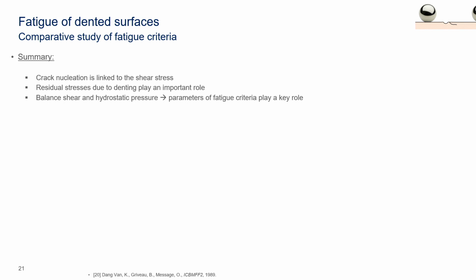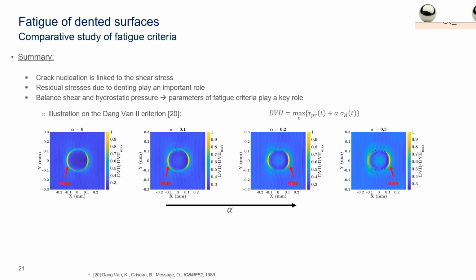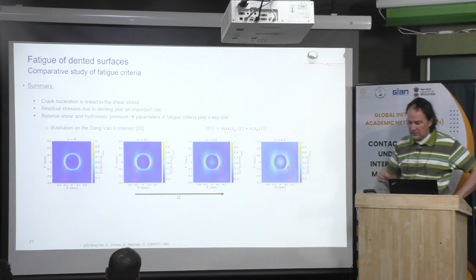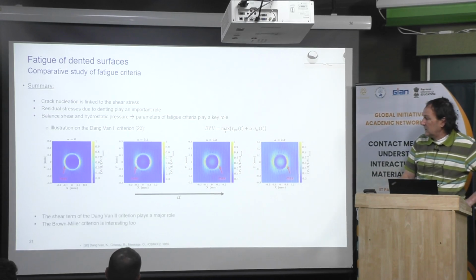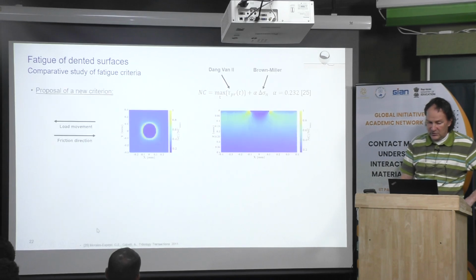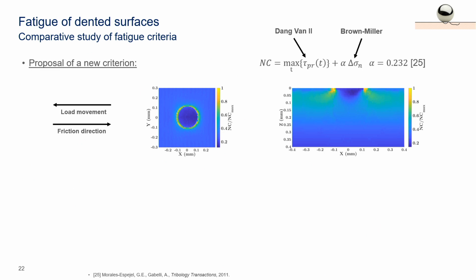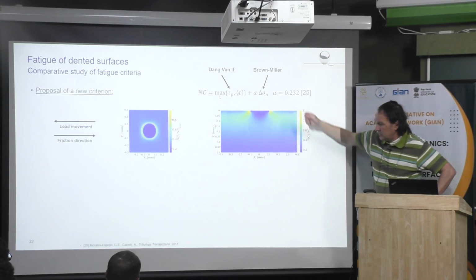Okay, then with all your different criteria, you can choose the one you think is appropriate for your problem. And typically, we have been working also on the second Dang Van model, which is slightly modified. We are also able to find where the crack could initiate. And then we choose the Dang Van criterion and also the Brown-Miller criterion to do the simulation. And at the end, we mix the two criteria. From the Dang Van, we keep the shear component, and from the Brown-Miller, we keep the normal component, in fact, in terms of stress. And also, we found in the literature the value for that.